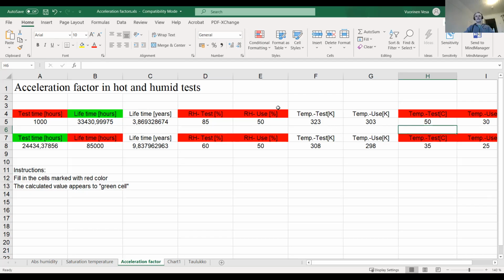So this is just showing how fast this acceleration happens when you change either the relative humidity or temperature in the test. Or if you want to simulate, for example, a lifetime of 10 years, here we have 10 years, and this indicates the test time in hours if we have certain conditions. So if the use conditions are 25 degrees centigrade and 50% relative humidity, and we use testing conditions which are 35 and 60, then the acceleration is really small. Our testing time is 24,000 hours, so it's more than 2 years. The acceleration factor is maybe 3, so this is almost 3 years.